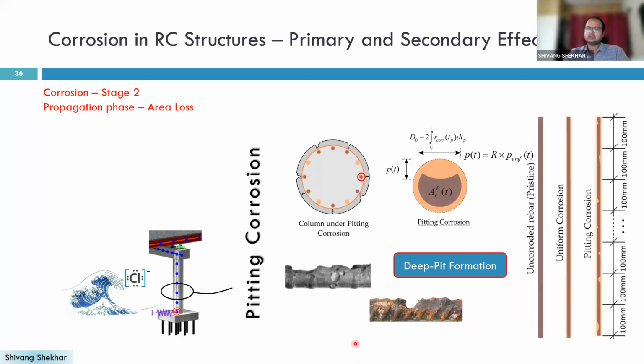One of the most widely used models for the cross-sectional loss of a rebar in chloride environment is a hemispherical kind of shape. You can see that there is a uniform area loss, and then at some locations pits are formed. This is a cross section, just a representation. If we look across the height of the rebar, uniform area loss is there, and at different locations pits are formed. Pits forming means much more area loss. People idealize these pits as a hemispherical shape.